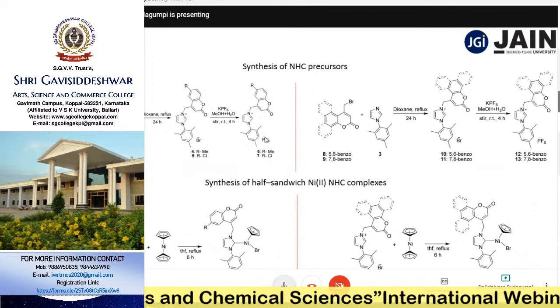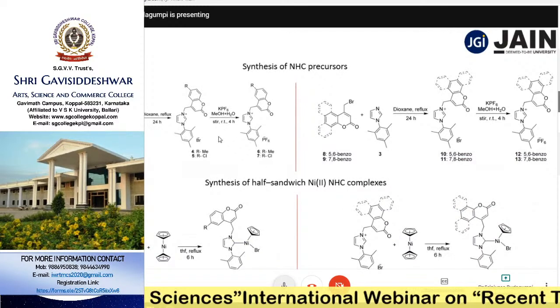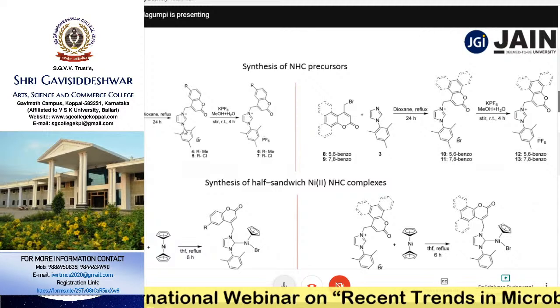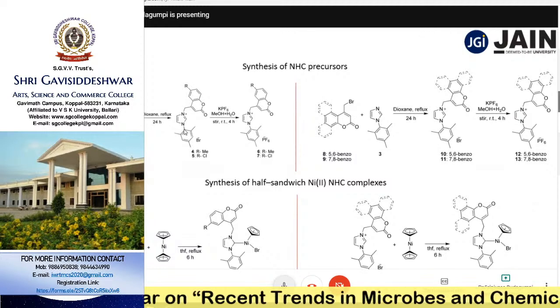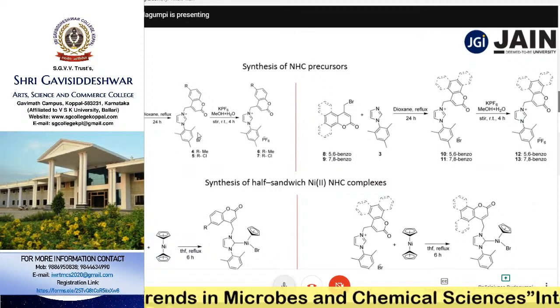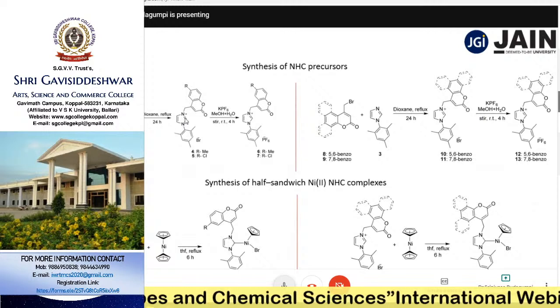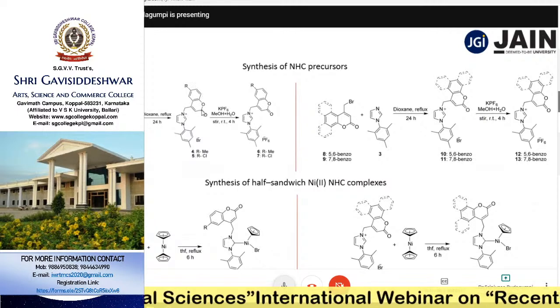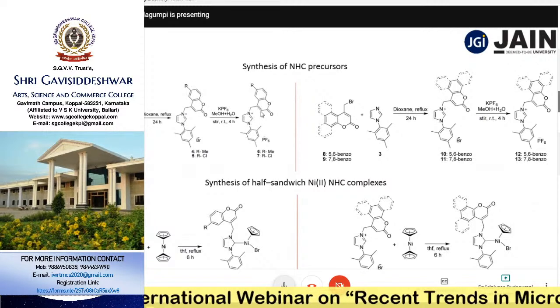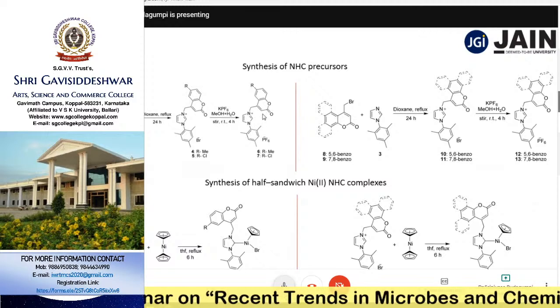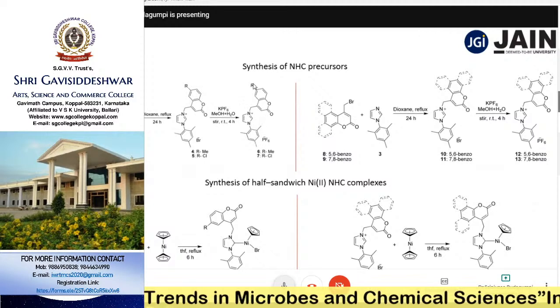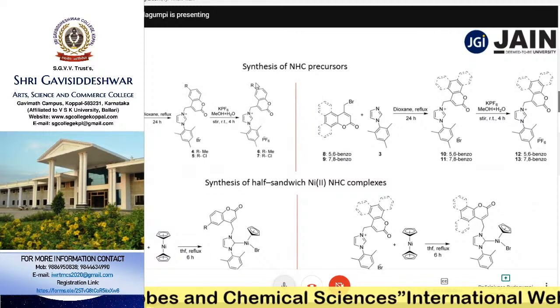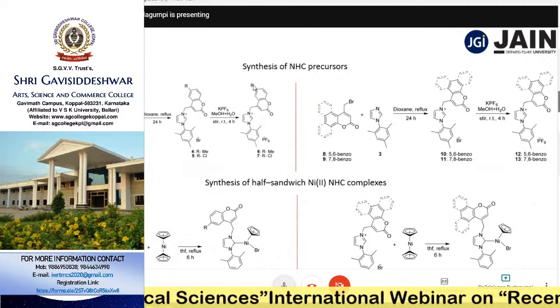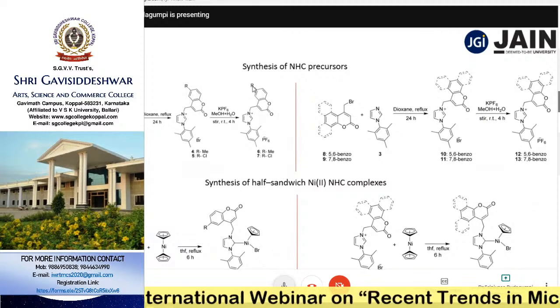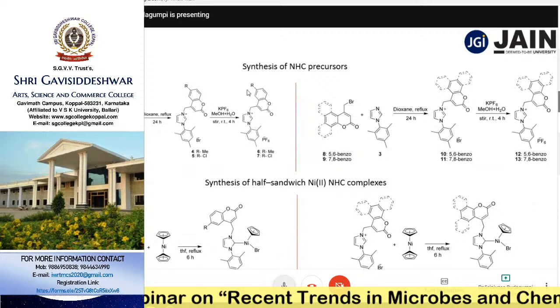This is almost the way we have seen in the palladium case. Right? So instead of alkyl substitutions here, we have aryl substitutions. That is, a mesityl-substituted imidazole system is here, along with a coumarin substituent. Again, we expected the involvement of C3 of coumarin, but that did not happen. In the previous case we had this methyl substitution, but in this case we have electronically modified the coumarin substitution, that is, a methyl group is there and a chloro group is also there.